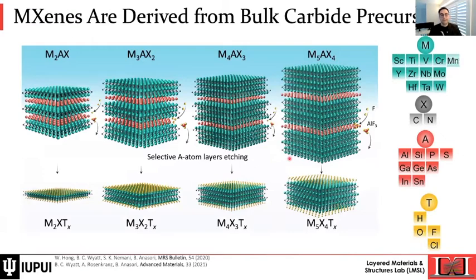This is how MXenes are synthesized. They are made by top-down synthesis, so it's not a growth mechanism. First, we need to synthesize the precursor of MXene, usually called MAX phases, which are ternary carbides and nitrides, where we have these 2D layers, but they are bonded with a layer of A-group elements, an A-group element being aluminum, silicon, and others.